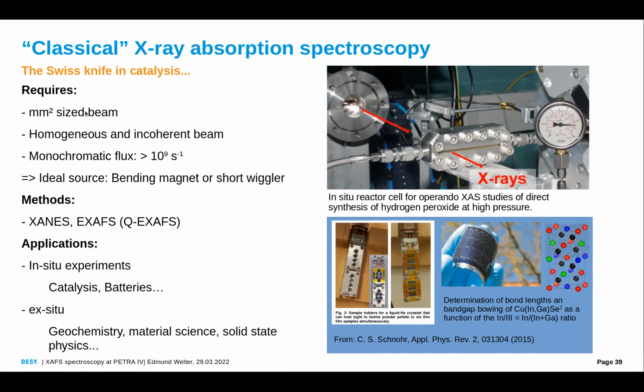So classical X-ray absorption spectroscopy, as I mentioned several times, is what I understand under this word: a millimeter-sized, square millimeter-sized beam. Homogeneous and incoherent beam, if somehow possible, a monochromatic flux which is larger than 10 to the 9, preferably 10 to the 11, 10 to the 12 photons per second, with not too much power density or flux density. And obviously the ideal source would be a bending magnet or a short wiggler.